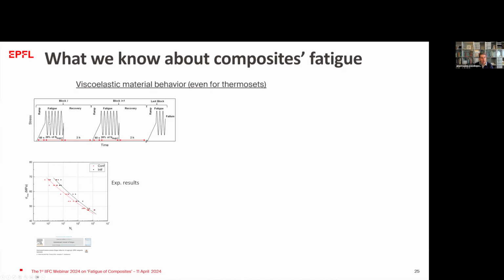So what we did, at the same amplitude, was interrupt the test every 20% of the average life at its stress level. What we've seen is that the life of the material has been extended by a factor of more or less 2, which means that there is a significant effect of this relaxation. The material relaxes when we stop the testing and recovers. And then we can start again at the same loading level, and we can extend the lifetime.